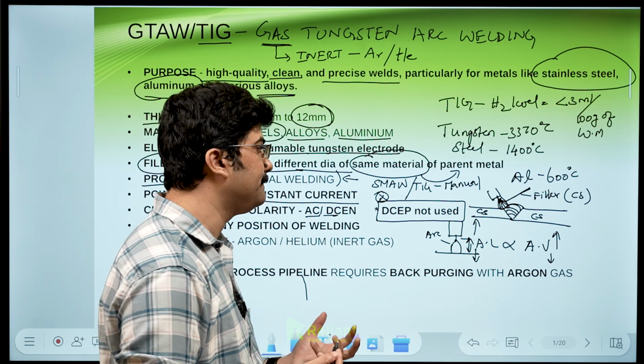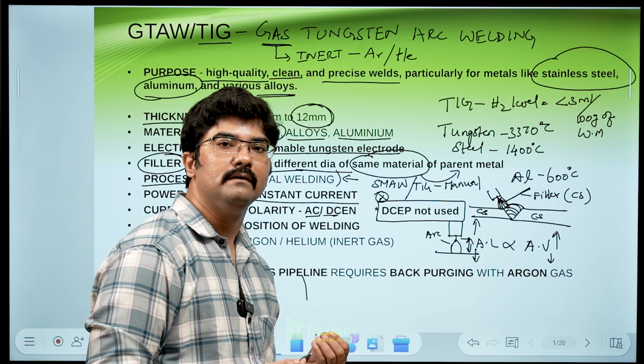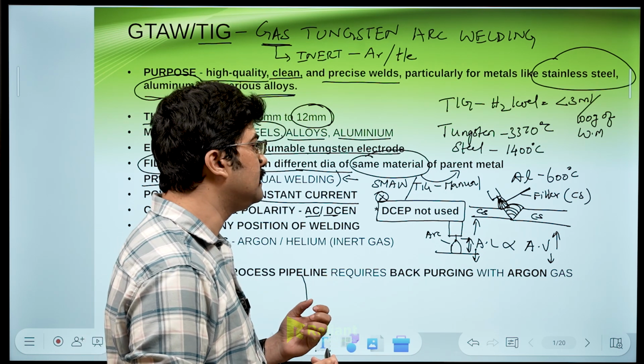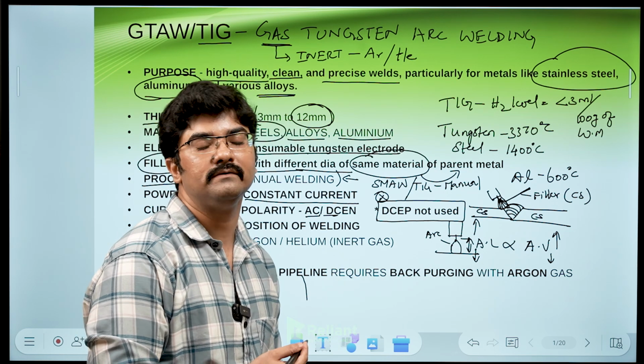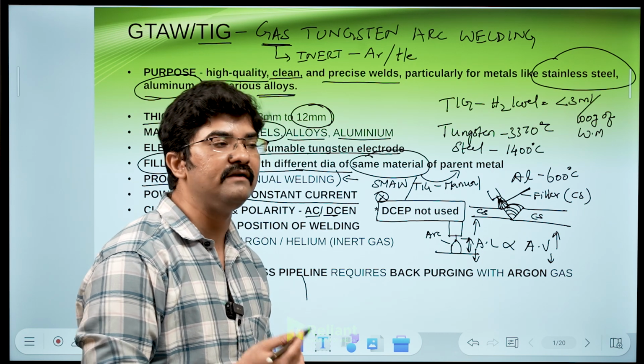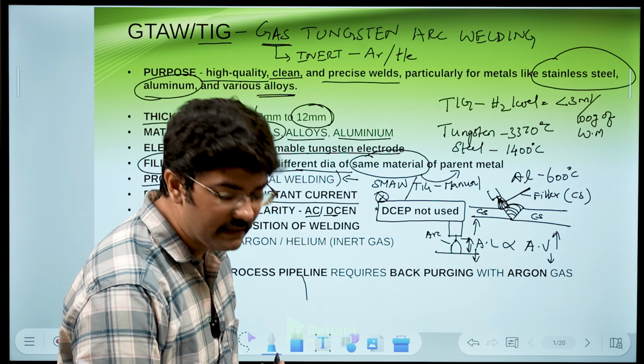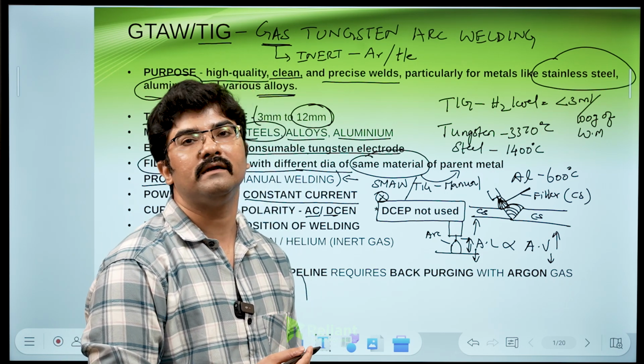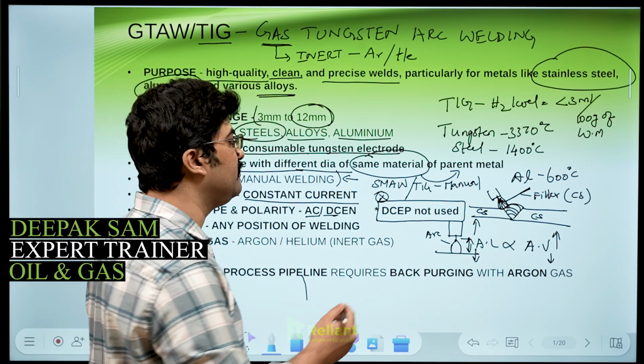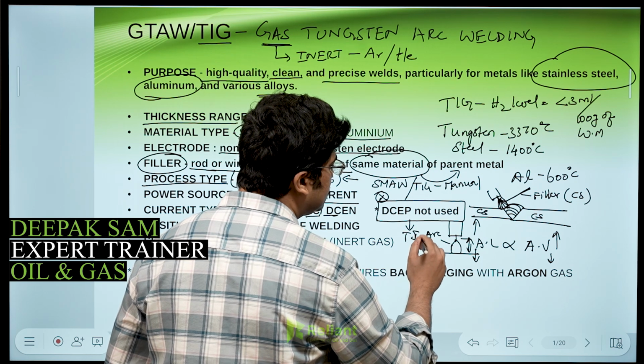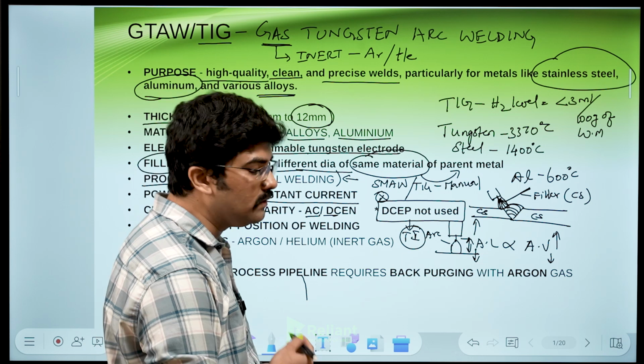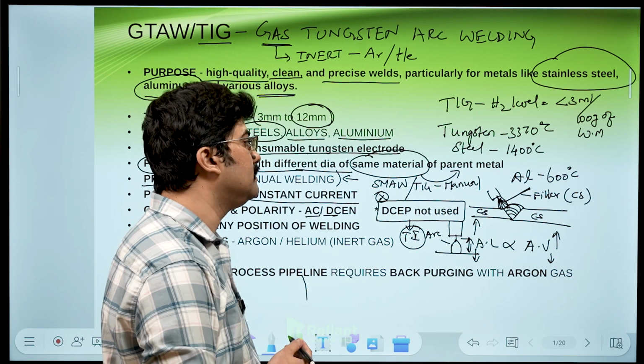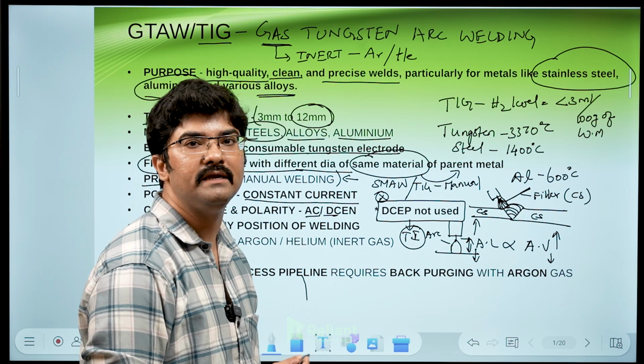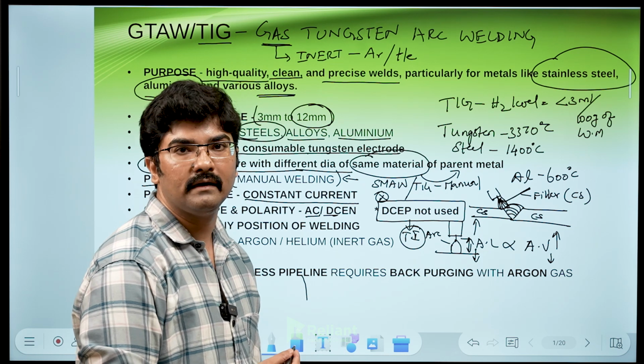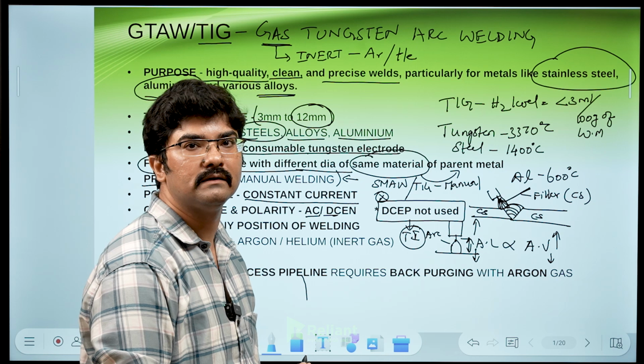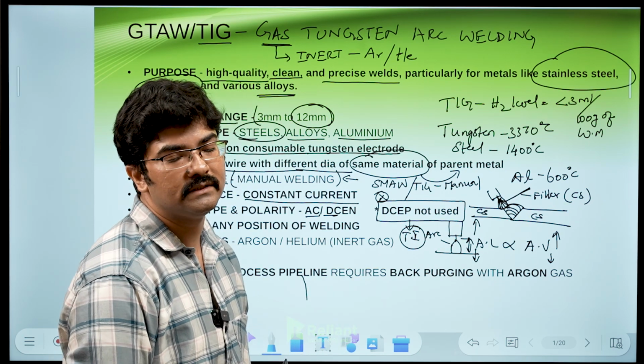Due to the high heat, DC EP makes the electrode overheated, and sometimes the tip will break and fall into the weld pool, and later we can identify that in radiographic testing, and while doing our interpretation in RTFI, we can find tungsten inclusion. So that is the major problem. If we use DC EP, we get tungsten inclusion. Also, too much heat is produced, then variation in heat input, fast cooling effect, cracking can also happen. So considering many criteria, DC EP is not at all used in the TIG welding process.